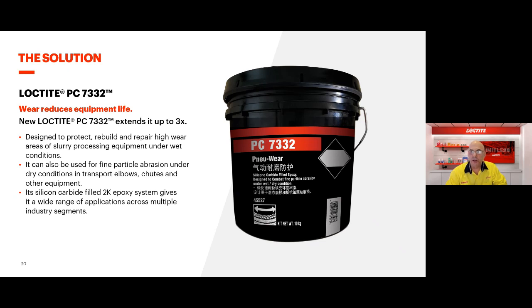And in tests that we've done, quite often it has extended the life of the pump or the pipe work by up to 3 times. And where we've got competitor products in the same location, quite often we achieve the same sort of life extension over the normal or the competitor wearing compounds. So, for example, a mine site might be using a wearing compound in a pump because they want to prolong the life of this pump. They've applied the PC 7332 and found that instead of having to rebuild that wearing compound every shutdown, they're having up to 3 shutdowns or more, where they don't have to rebuild that wearing compound because the PC 7332 is outlasting the competitive wearing compound significantly. Next slide, please, Shevlin.